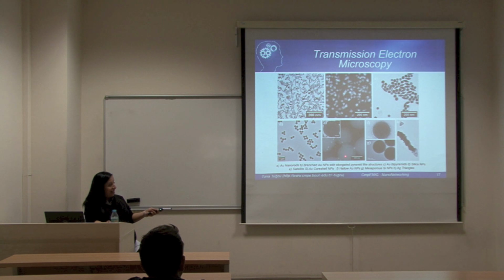And by just melting the silica inside, you can have such a structure. This is a gold bubble or gold halo structure, you can say. You have gold outside, and inside there is nothing. Actually, this particle is obtained from this particle. We just melted it, it's like an explosion of the bubble. It's like you just put in a needle, the silica is gone, and then you have a gold halo structure. And we call it gold cages. And there are a lot of applications for this material.